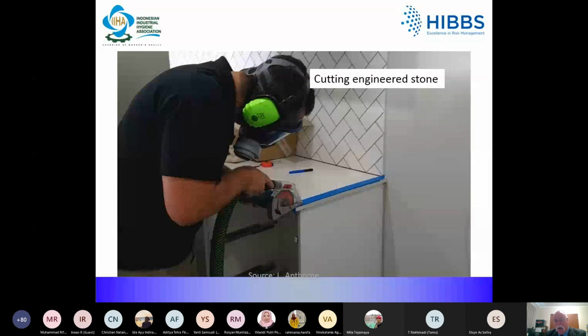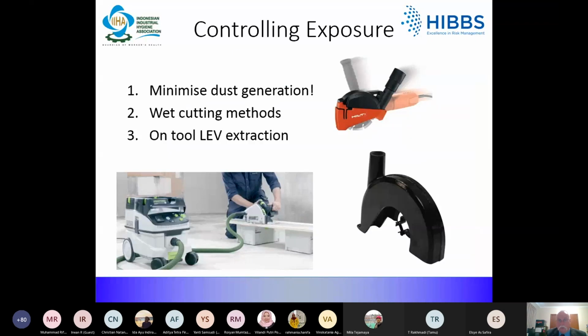And the cutting of engineered stone has really been a tragedy in Australia, because the engineered stone industry employs generally migrant workers, and there was little consideration given to the high levels of crystalline silica in the actual engineered stone, as it can be up to 90%. The cutting and grinding and polishing of it releases quite significant quantities of RCS, and that has resulted in a significant outbreak in Australia amongst these trades of acute silicosis. And as I said before, it has tragically led to premature deaths. And when I say premature, I mean very premature. Men in their 20s, 30s and 40s have died as a result of this exposure.